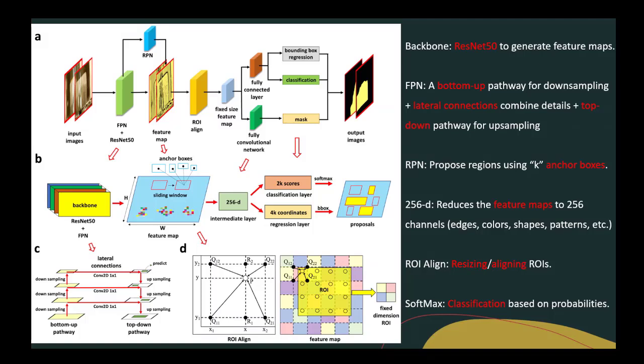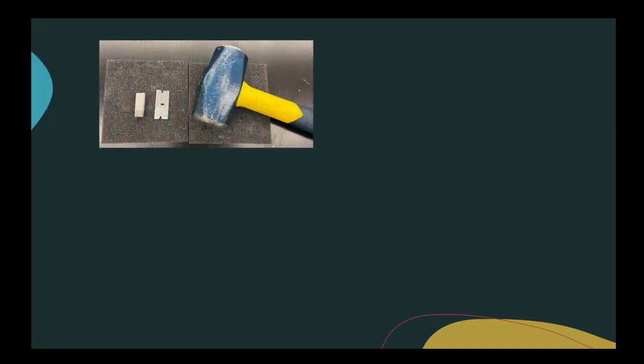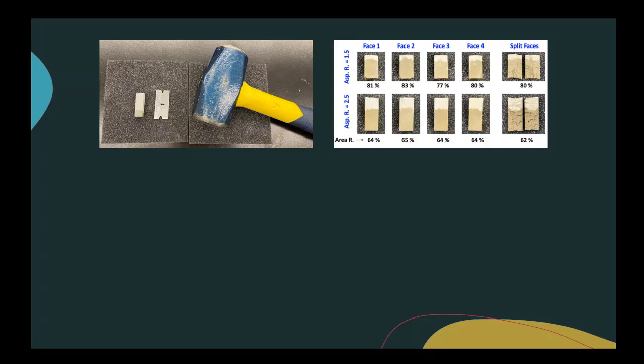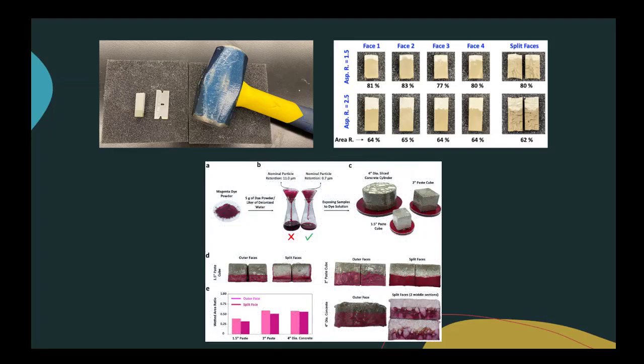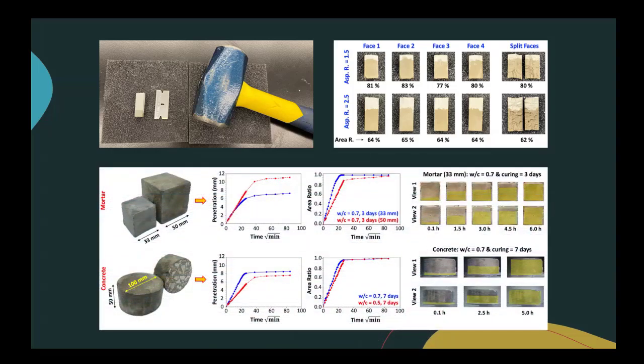So one valid question is, I see this water level here. Does it represent what is happening inside of my sample? So I took my sample and I split it in half using a razor blade and hammer. And you see that on the split faces, the water level is comparable. So what about concrete? We couldn't use just water because we need something to cut it. So I used dye solution. So this is the dye solution that came in contact with concrete. And after drying, look at this sample, the water level is comparable to what we see on the outer surface. So this method is applicable to mortar and concrete samples.